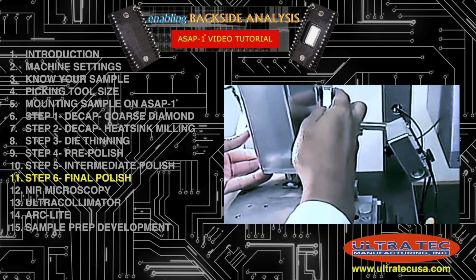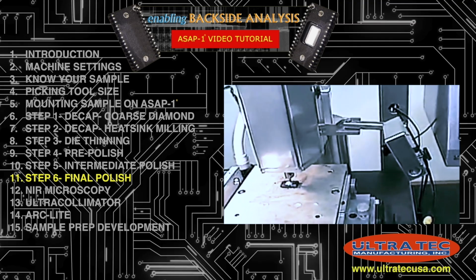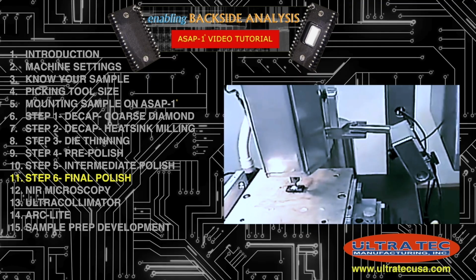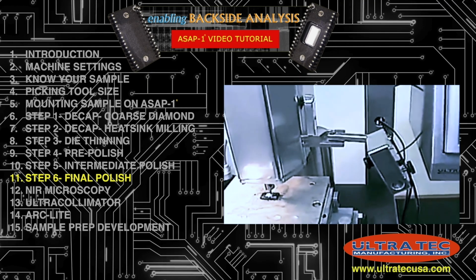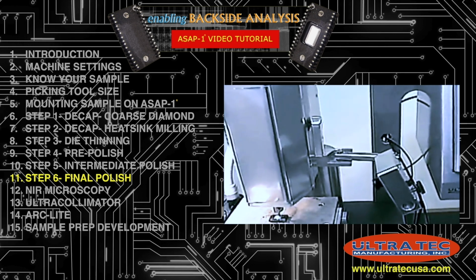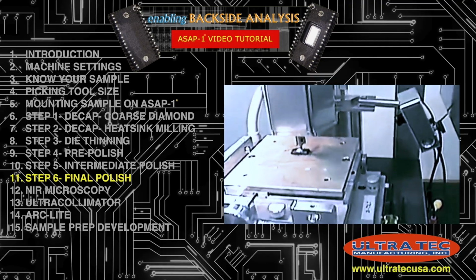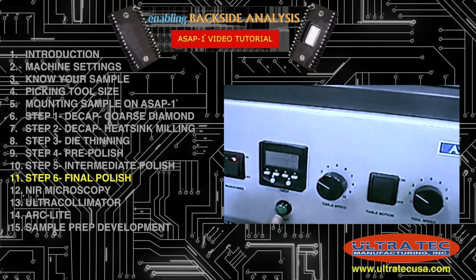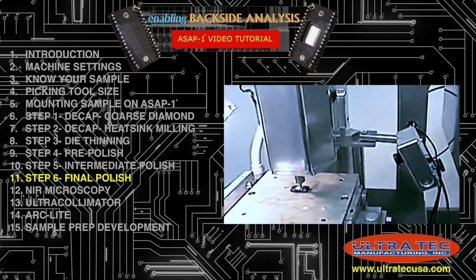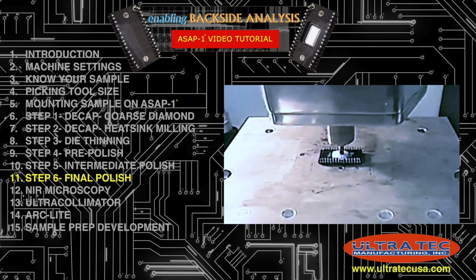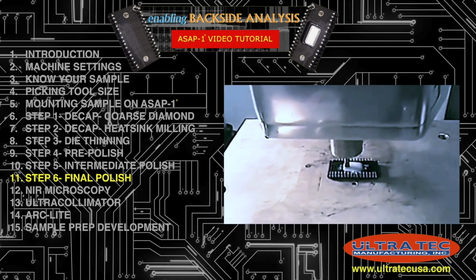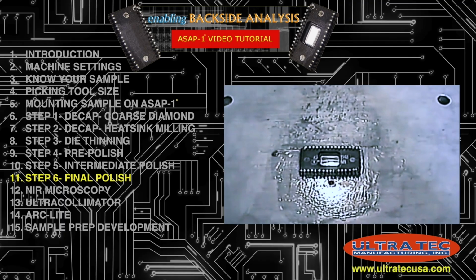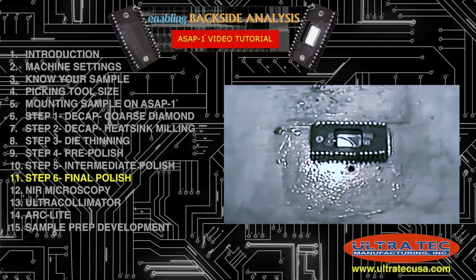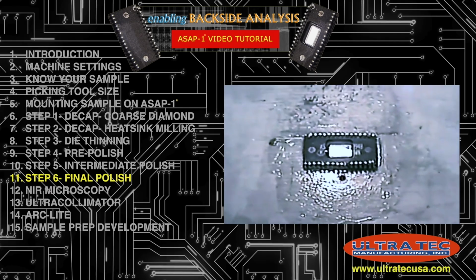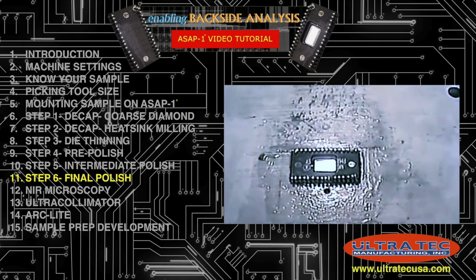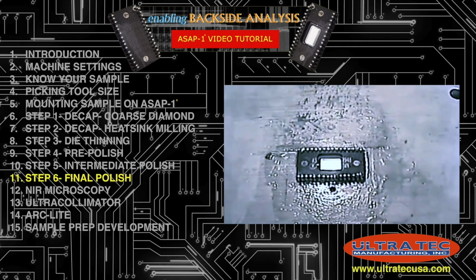Lower the floating head. Set 30 microns of applied pressure. Set the timer to 5 minutes or 300 seconds and press start. When the timer runs out, the polishing process is complete. Clean the sample thoroughly. If a mirror finish is observable on the sample, you can move to backside imaging.